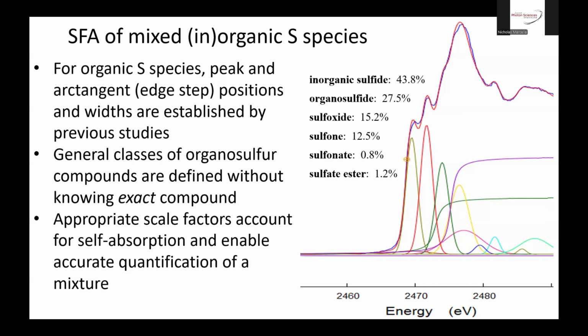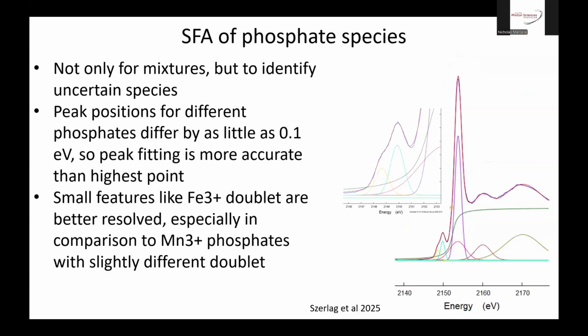I've actually helped people in some cases, when they were insisting on using linear combination fitting, to use a more and a less self-absorbed spectrum for each standard that they have for the linear combination fitting. And that helped a little bit, but I favor this method for sulfur and phosphorus because there are so many experimental variables. And for phosphorus, it's not spread out so nicely as for sulfur. So it's not necessarily as useful for multiple mixtures, but it is useful for identifying uncertain species.